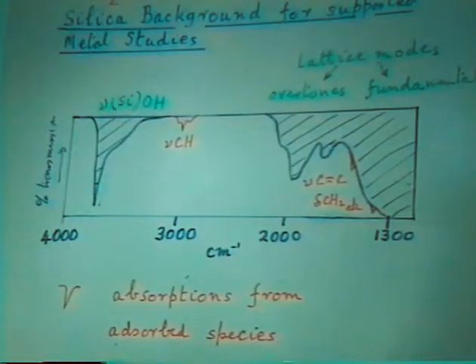And that gave us a very nice window in the region of 3000 wave numbers where the CH stretching modes are. So that was what we aimed at, and of course, before we published anything, Bob had published some very nice spectra of hydrocarbons on a nickel silica catalyst. At that time, we didn't have the ratioing facilities, and we found it difficult to be certain about the bands down here because they're relatively weak in the angle deformation region, and they're on rapidly sloping backgrounds. Bob had a rather carefully contrived way of doing that at a very early stage. So we said, let's look at ethylene on platinum, and let's see what we can find.